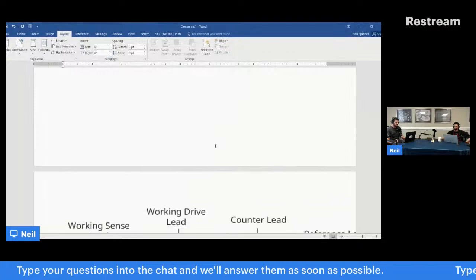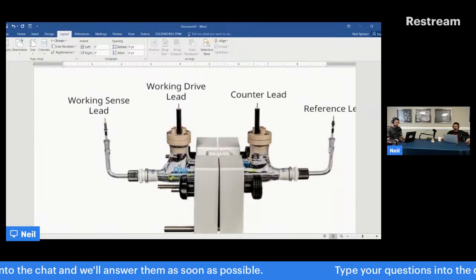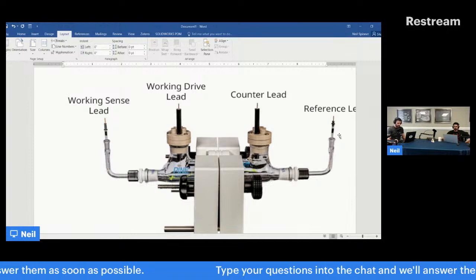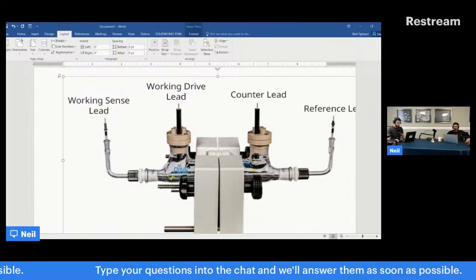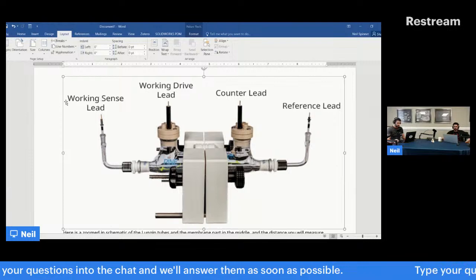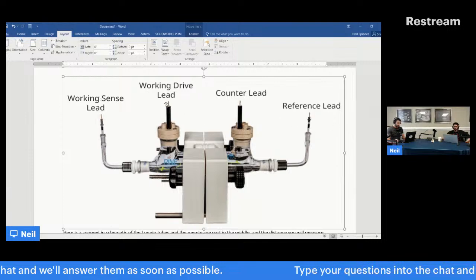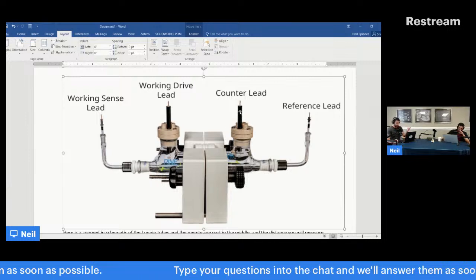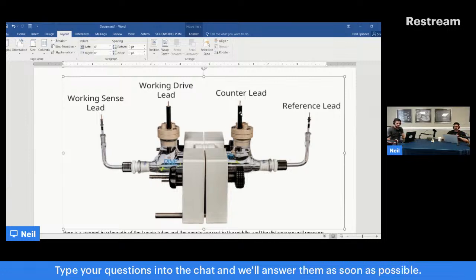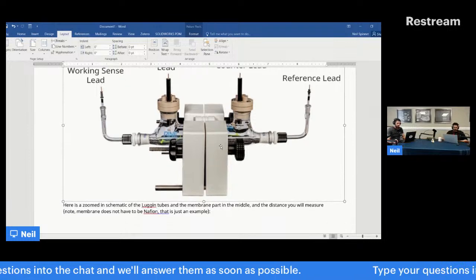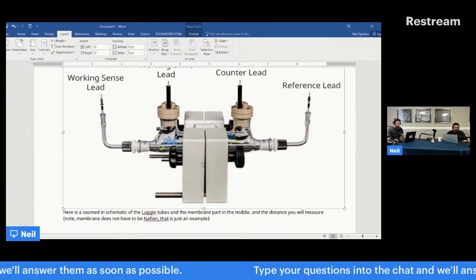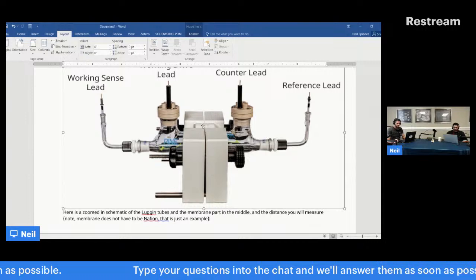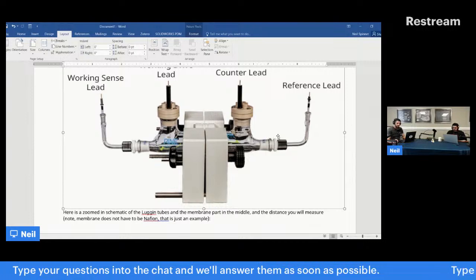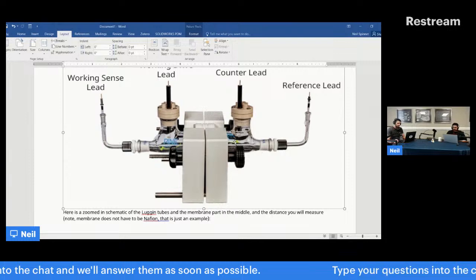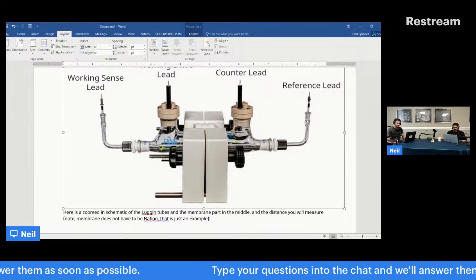This one. So the setup is something like this. You'll have, I know this is kind of off the screen here, I'll try to make it a little smaller so you can see. You have two reference electrodes on either side, and then two, usually just platinum coil, any sort of working electrode. And basically this is like a cross section of this. You have the membrane in the middle. You can't probably see it here, but there's a membrane in the middle. There's two long Luggin capillaries that go all the way to the middle, and the reference electrodes are in those, and there's solution there.